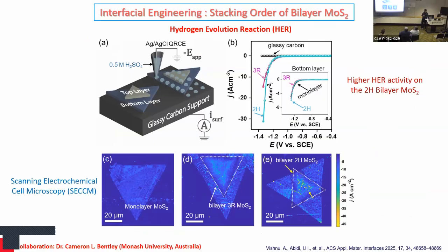Again, we did this in collaboration with Cameron, we did HER applications and HER visualization. So in that case, interestingly, we again see if we just change the stacking of 2 different bilayers, the activity of the HER is changing. So in our case, we see in 2H MoS2, which is like a 60 degree rotated bilayer, higher activity as compared to the one in which we have a 0 degree rotated bilayer MoS2.